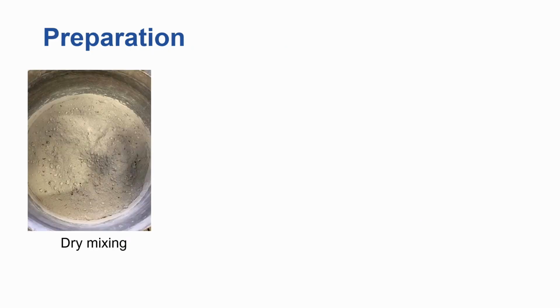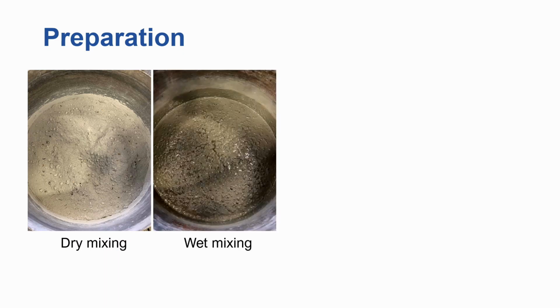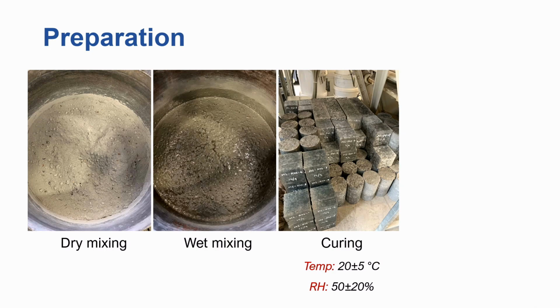So this is the preparation process. I mean, quite similar to normal concrete, mixing the dry ingredients. So I did this in the lab for about 5 to 8 minutes, and then adding water and mixing for another 5 to 8 minutes, and then casting and allowing the specimens to cure. So we cure them under ambient laboratory conditions.